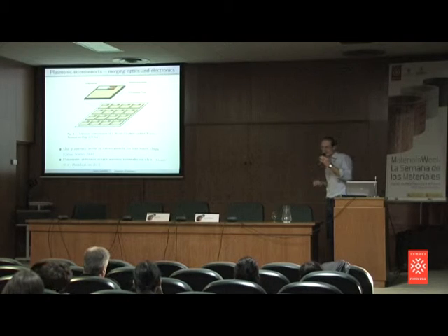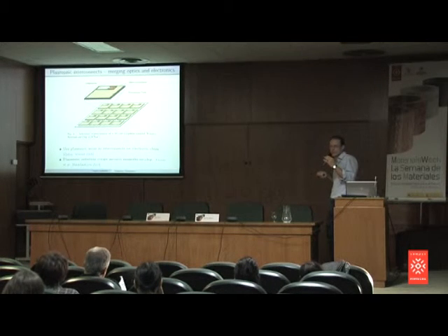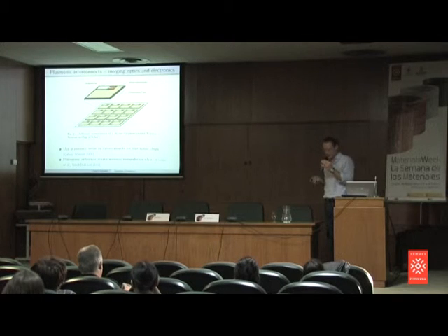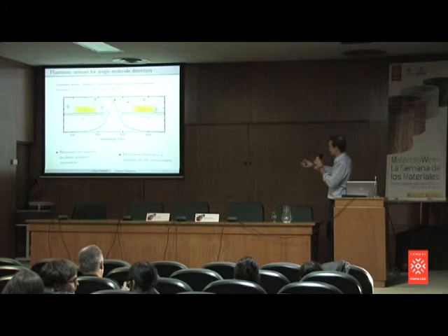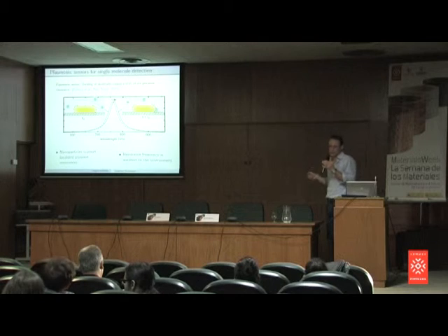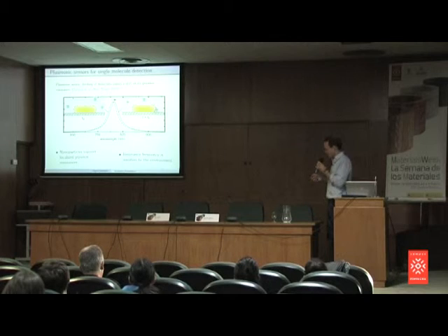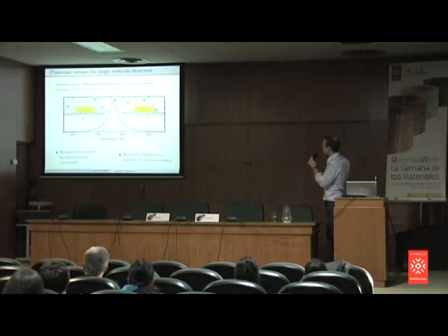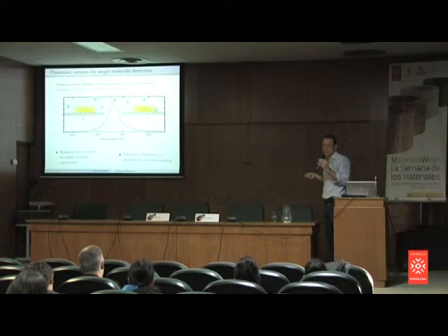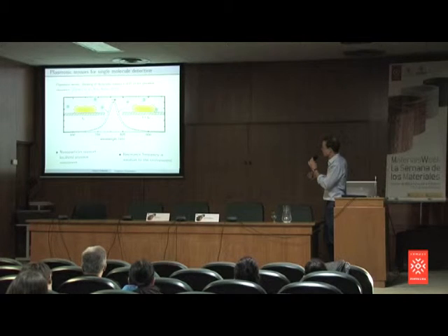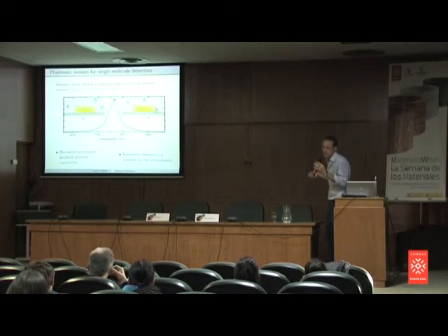And I have one more application, and that's the only one to my knowledge which is so far commercially available of those I show. But this here already for sure works, but has nothing to do with graphene as I show it here. Plasmonic sensors. Now what we see here is a very small gold particle, a nanoparticle, a couple of microns long. And it turns out if you shine light on this with the right resonance frequency, then you can make the electrons in there go like whoosh, whoosh, whoosh, like a standing wave, which is a plasmon oscillation.